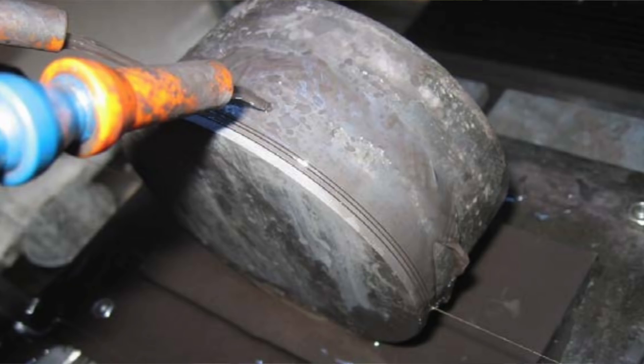The conventional way to get silicon wafers is to grow a large boule — a single crystal of pure silicon — which takes about a month. Amorphous silicon is only about 5% efficient; you need a perfect crystal structure for higher efficiency. This is electronic-grade silicon, more expensive than what the solar industry currently uses. After all that time and energy growing the ingot, you cut out wafers — and when you do that, you waste half the raw material, because the saw blade itself is 200 microns thick. You lose a wafer for every wafer you cut.